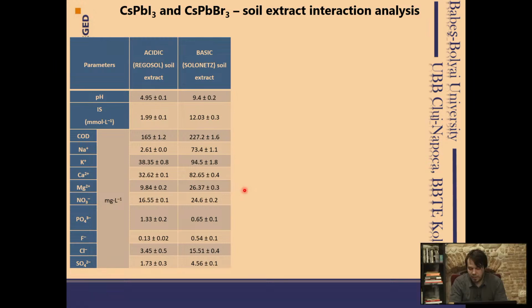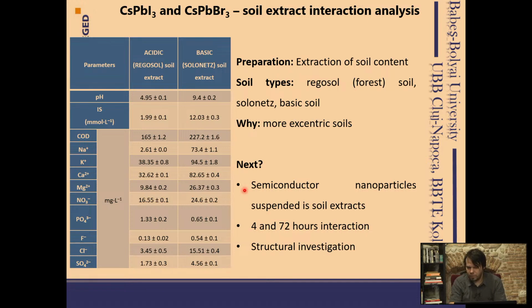However, what we did, in fact, is a so-called soil extract, which is a very easy thing to do. You can take a cup of soil anytime from your garden, put it somewhere which water goes through, and make an extract of that soil. So all the components which are in the soil and are water soluble can be retained in the form of soil extract. We have taken 2 types of soils, one slightly acidic and one basic soil. And we did a very simple experiment. We just took these materials which were for solar cells, the optical part, and put them in a suspension, a kind of tea made from these materials. And after a specific time, we took 2 times, 4 and 72 hours, and we analyzed the composition of these materials.